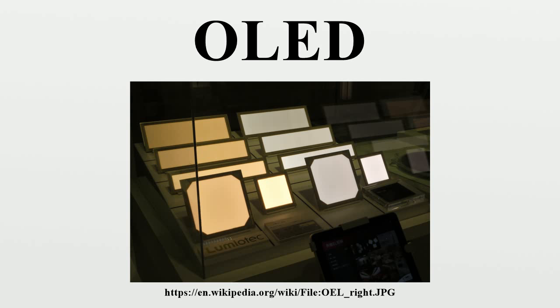Ching W. Tang and Stephen Van Slyke at Eastman Kodak reported the first OLED device in 1987. This device used a novel two-layer structure with separate hole transporting and electron transporting layers such that recombination and light emission occurred in the middle of the organic layer. This resulted in a reduction in operating voltage and improvements in efficiency that led to the current era of OLED research and device production.